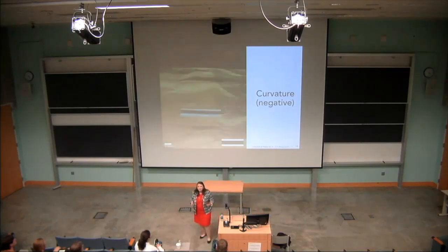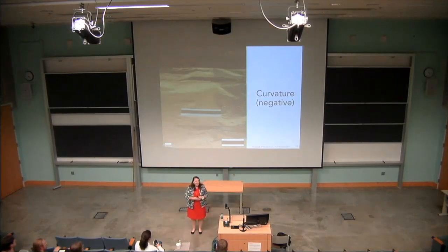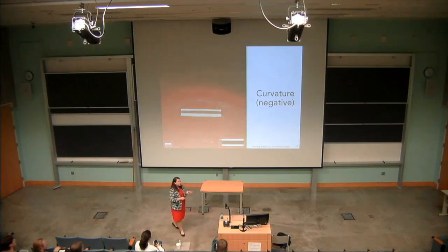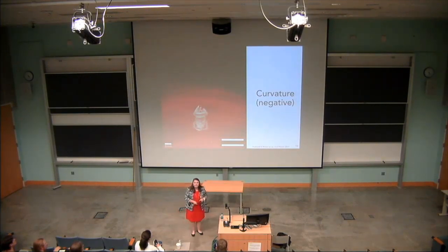But then our next question became, what happens if you inverse that design, right? So now in this case, I have the exact same geometry, the exact same amount of ink, but I've placed ink along the center portion of that material. In this case, if you can imagine that idea of having one single fold, just a part of that cube that I showed you earlier, you can have one panel lift upward by placing a line. So what's interesting is when we play this video, it's a two-step response. First, it folds over in one direction. And then, because it's a biaxially strained material, it will wrap around and generate a resulting structure that has negative curvature.